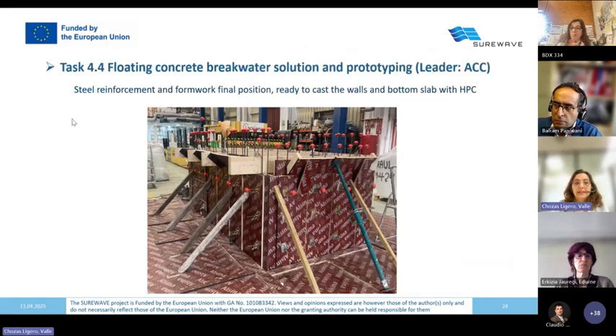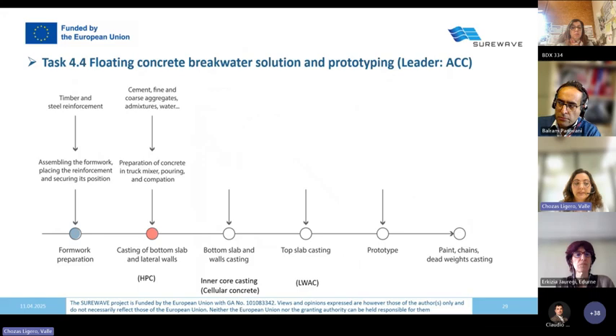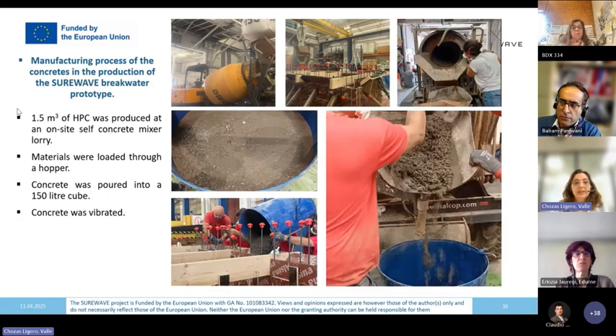Regarding the prototype, this is the steel and formwork in final position, ready to cast the walls and bottom slab with high performance concrete. The manufacturing process of the prototype was casting the bottom slab and lateral walls. There are several pictures. We rented a self-loading concrete mixer lorry. Materials were loaded through a hopper, and concrete was poured first into the cube and then into the prototypes.